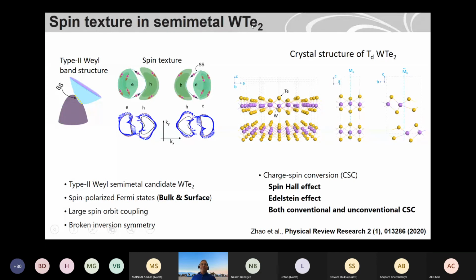For example, I start with the topological semi-metal called tungsten telluride. It can be in the 1T' phase or the Td phase, depending on the temperature. There is a calculation showing that there is a spin texture in this material. This is the paper which I refer to. There are spin textures in these materials for the electron and hole pockets at the different Weyl nodes. This is very interesting because this material has broken symmetry, and it's only symmetric along these two planes, while the other planes have broken symmetry.